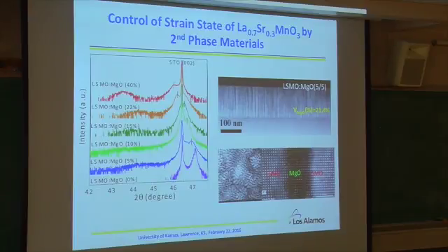That's several parameters you can do. So you control the volume ratio, and you can also use a different substrate. You can also change the material. Here I just show you MgO. Actually, when you use zinc oxide or ceramic oxide, they will give you different results.